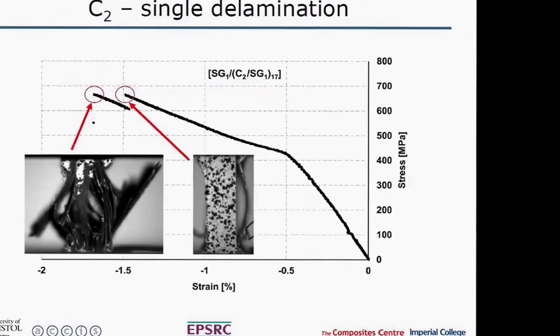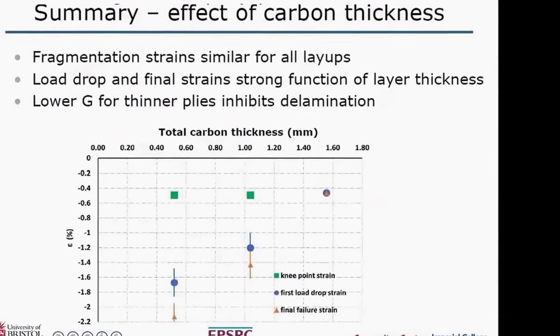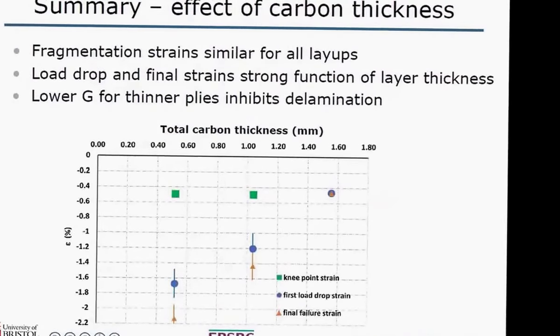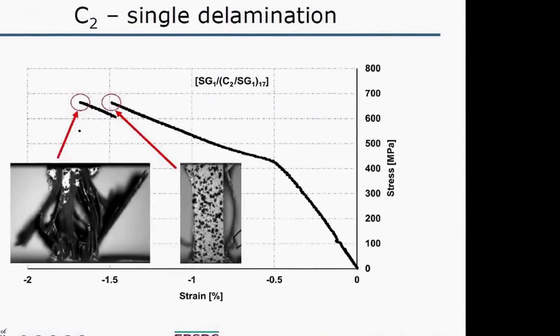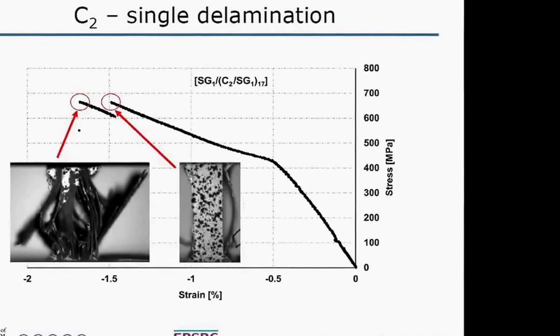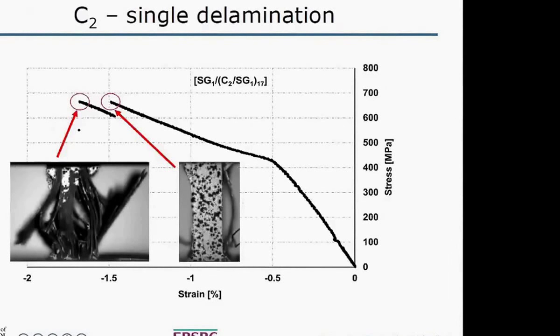When you have fewer carbon plies, in this case only 2, then what happens at this point here is we get past the fragmentation stage, and we get this increase in load, which is now the glass taking more load. The carbon is carrying about the same load all the way through there, but the glass is taking more load. So that's why the slope is much lower, because that's effectively the slope of the glass plies.